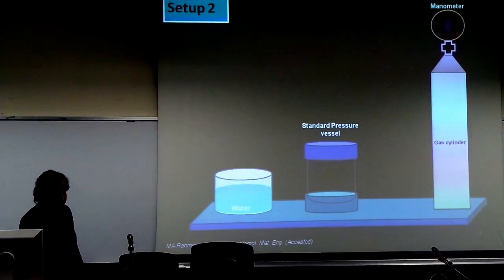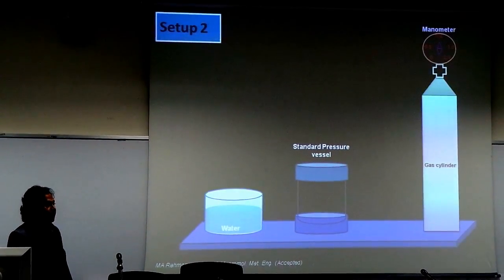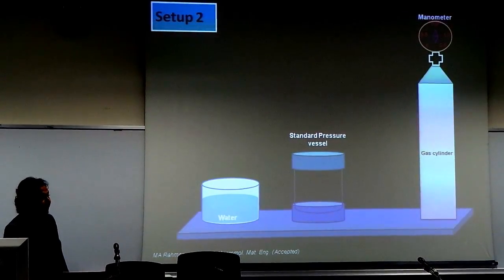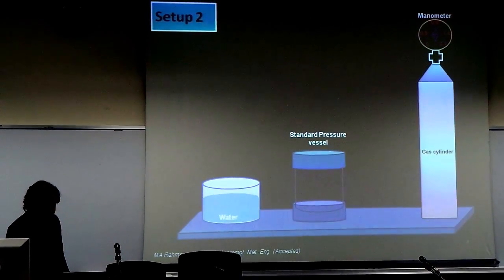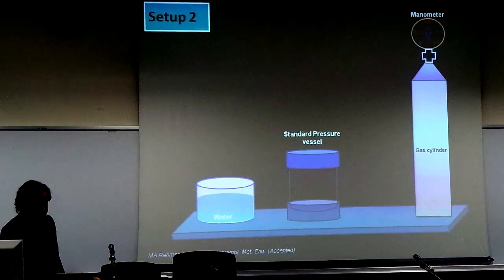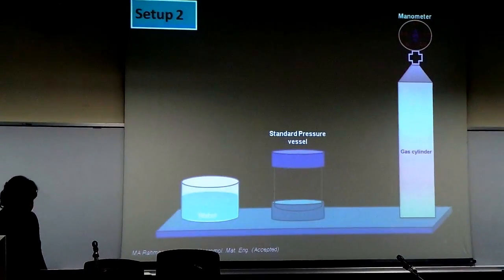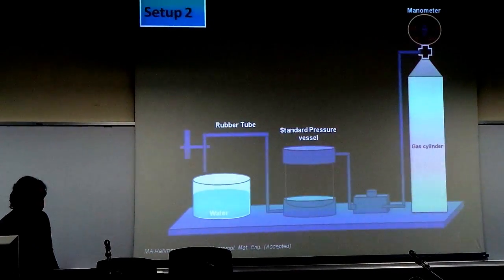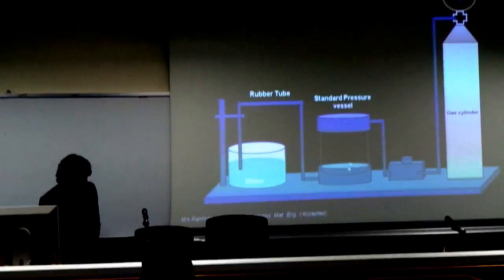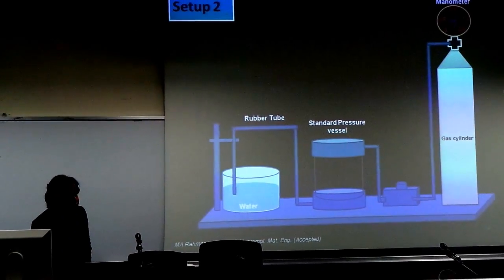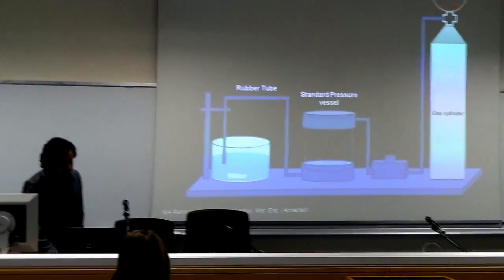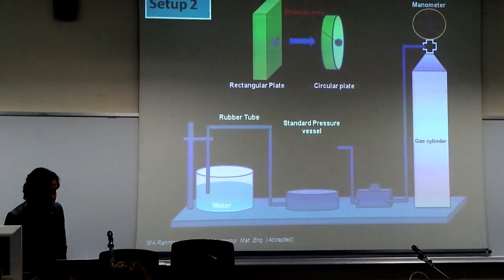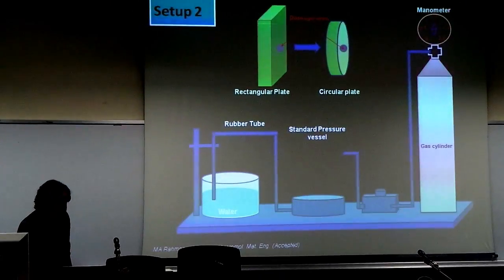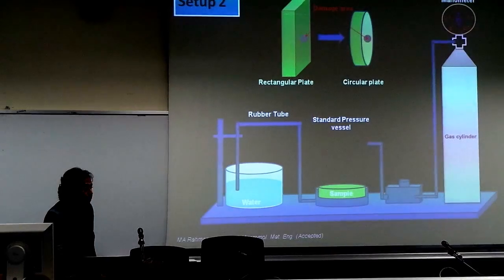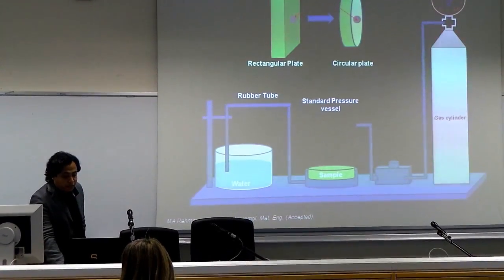And in the second setup, I have a manometer where I can use a different pressure difference to identify the healing efficiency of the material. And each apparatus in this setup was connected through a rubber tube. And since the base of the standard pressure vessel is circular, I have to prepare a circular sample from the rectangular sample, and then the circular plate was inserted at the bottom of the standard pressure vessel, and it was closed with the upper part of the vessel.